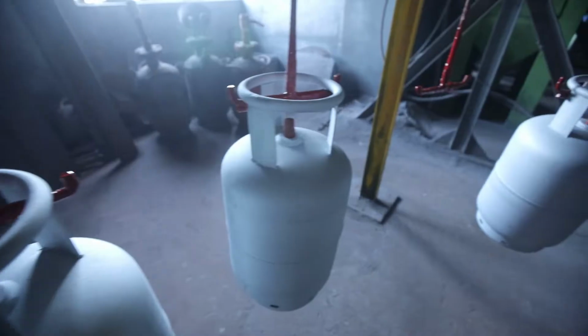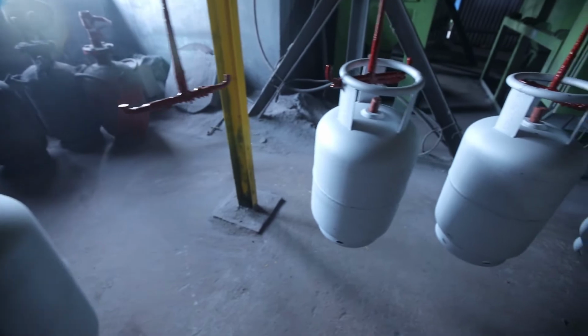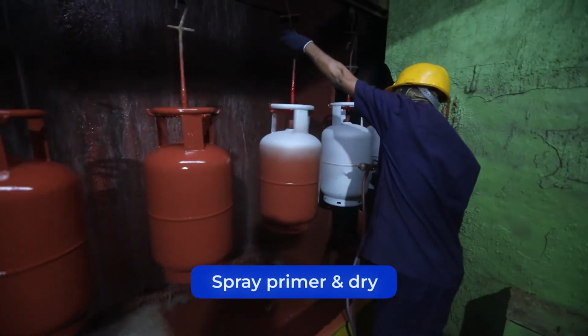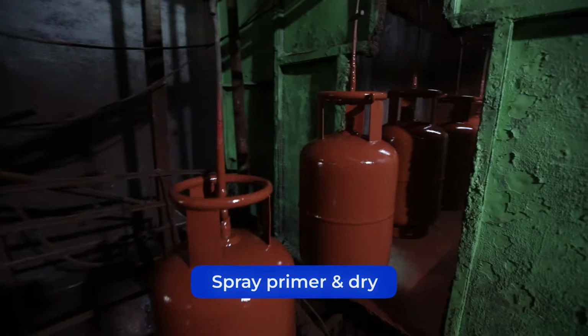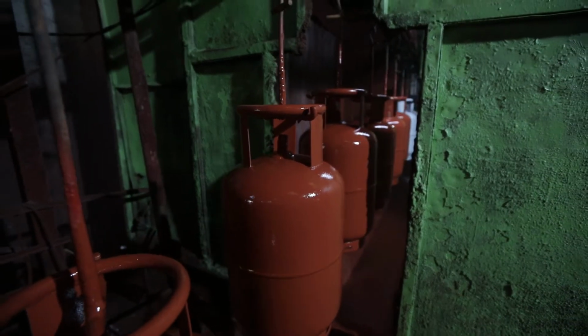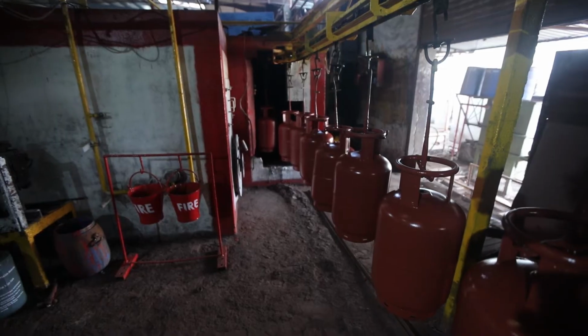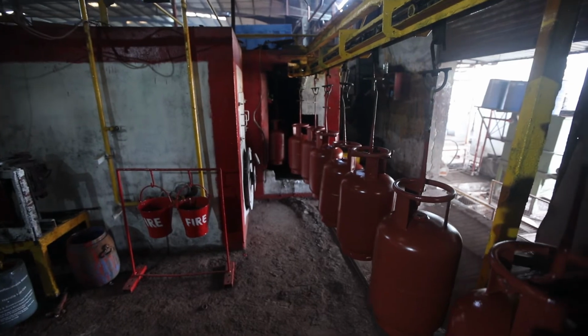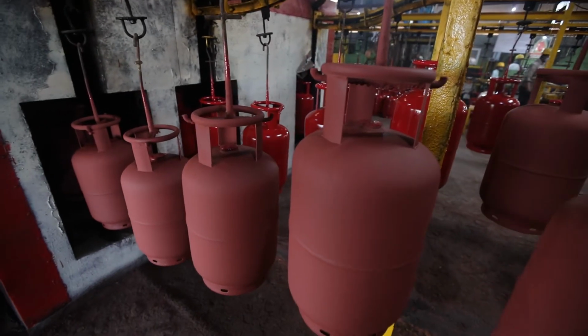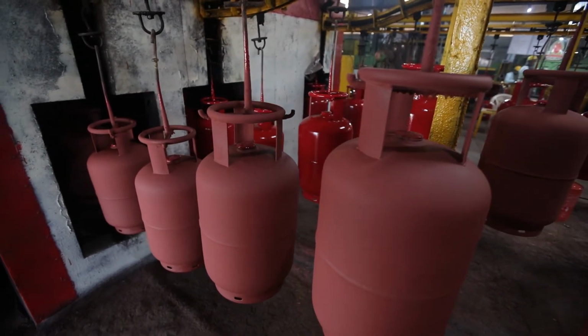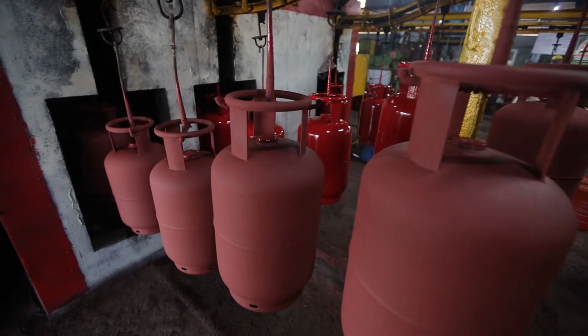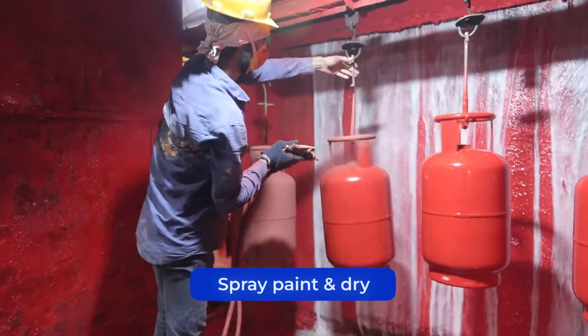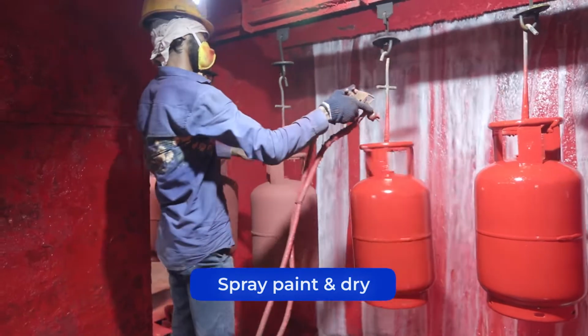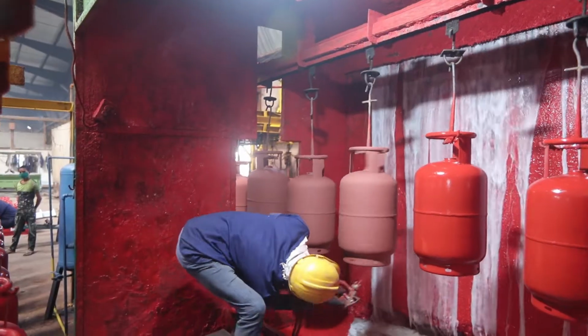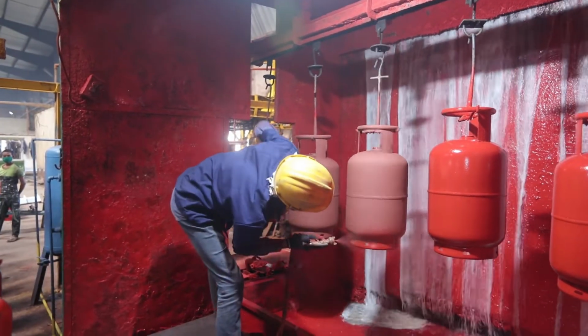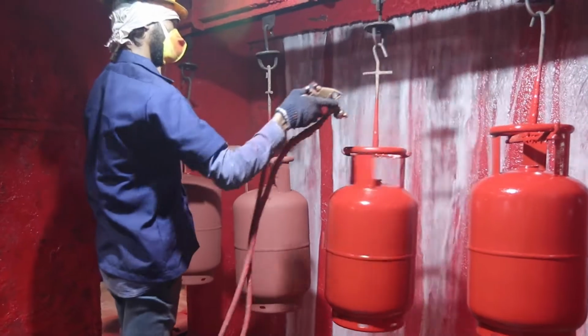While painting, the cylinder is rotated on a conveyor with a hanger in the primer painting booth. The paint is sprayed in a way to obtain not less than 15 microns thickness all over the primer painted surface of the cylinder. The paint dries after going into the oven at approximately 80 degrees Celsius. Total coating thickness of zinc, primer and paint should not be less than 67 microns when measured with a coat meter or as per customer requirement.